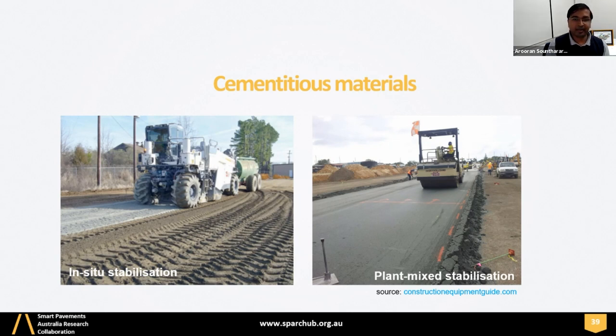All right, the next material that I'm going to cover here is cementitious material. Previously we discussed the unbound material and its testing and design protocol. Cementitious material commonly includes GB, general purpose, general blend, and fly ash, and how this material is used in practice. There are two ways this material can be effectively used. One is in situ stabilization, which I mentioned earlier, a common practice in Australia for old or degraded pavements. The other one is plant mix stabilization, where you prepare the material in the plant by mixing the cement with the crushed rock, and then you bring the mixture to the site and compact it.